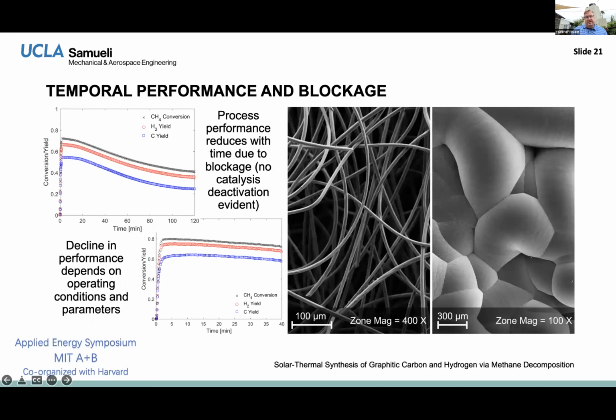So I said that we didn't have clogging issues. What I meant was, for a long time we don't have clogging issues, but then eventually we get this beautiful coalesced sample. So we start here with a very open, 95% porous medium. And then after an hour or two, you start to see this. And so we start to choke off our flow, at least in the hot spot. And so we see these degradations of methane conversion and hydrogen and carbon yield. So that is a problem. That's an issue for sure. But it's not one that I think is a showstopper at all.